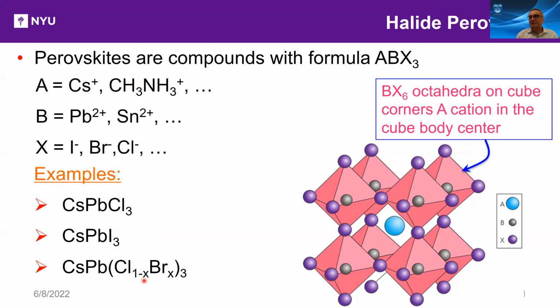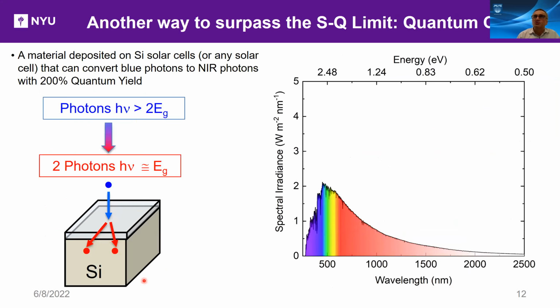Now, I want to get back to the problem of surpassing the Shockley-Queisser limit. I wanted to give you an introduction to perovskites because they're used in tandem solar cells, but they're also going to turn out to be important materials in what I'm going to talk about. However, the approach that we're talking about is another way to surpass the Shockley-Queisser limit, and it is different from the tandem solar cell. In this approach, one deposits a material on top of a silicon solar cell, and actually it doesn't have to be on top of the cell. It could be on top of a glass, which then gets put onto the silicon solar cell to encapsulate, for example.